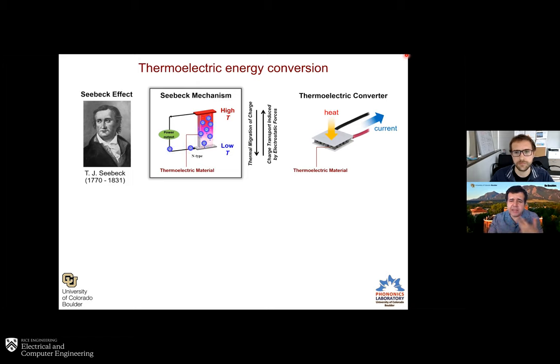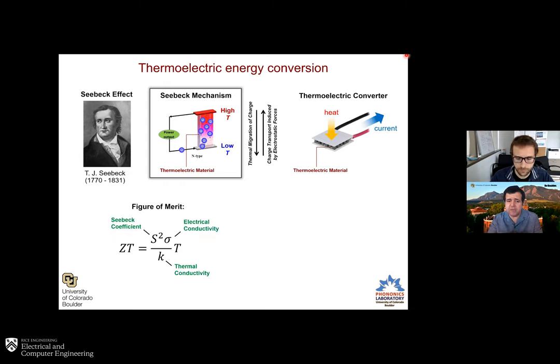And as one would imagine, a key aspect of it, of course, is how well it performs. So the efficiency of the device and inside the device, how does the thermoelectric material itself perform? So there's a figure of merit that describes that, what is known as the ZT figure of merit. It's basically a numerator divided by a denominator. In the denominator, you've got the thermal conductivity. And then on the top, you've got a product between the Seebeck coefficient squared and the electrical conductivity. So the Seebeck coefficient is a measure of the ability of a material to generate charge in the presence of a temperature gradient. And then, of course, sigma and kappa are the measures of electrical and thermal conductivity.